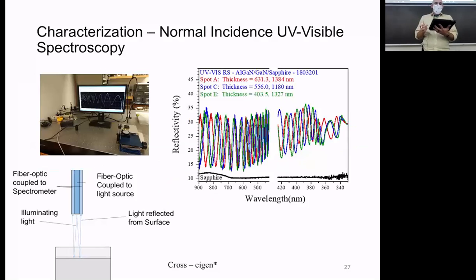After we did that, we'd move on to characterization. Because if you're growing material and you don't know what it looks like or what it's doing, you basically don't have any idea what you're doing. So the first thing that we did was we'd do normal incidence spectroscopy. And what that did was that produced an interference pattern that was related to the thickness of the material. You can see we had a fiber optic on the left that would shine down, and the light would bounce up through this material and come back up and be collected coaxially with the same fiber, and then broadcast to our computer from the spectrometer.